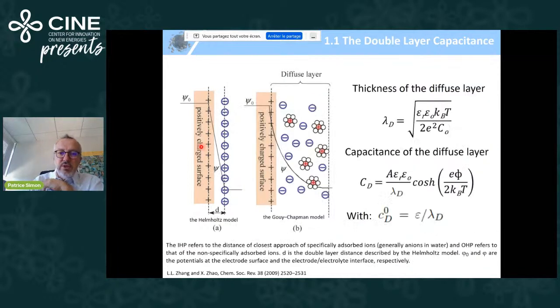So to tackle this issue, Gouy and Chapman came up with a diffuse layer model. In fact, you screen the electrode charge within a finite distance in the electrolyte, lambda D, which is the Debye length. And then you can calculate the capacitance for what we call the diffuse layer. This capacitance changes as a hyperbolic cosine. You can see this diffuse layer as the distance from the electrode to the bulk of the electrolyte where the electrode charge is fully screened.